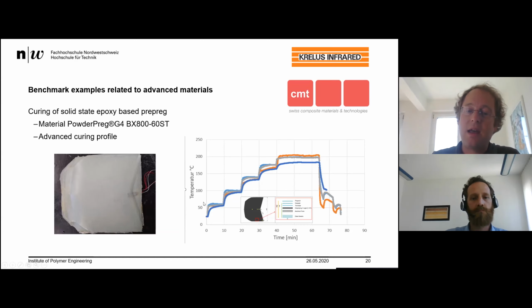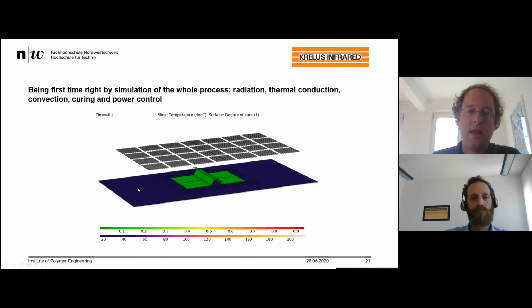And in this case, we used again this geometry, and we followed the curing process, which is shown here. So it's also possible to apply a heat rate or advanced temperature conditions.